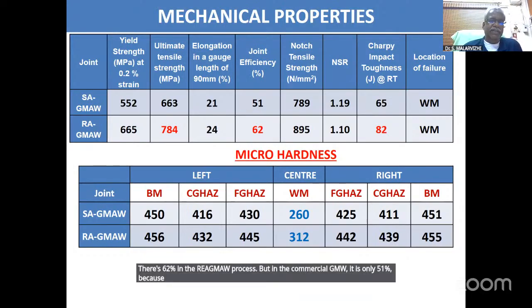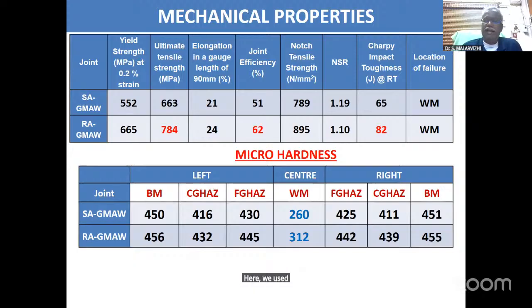Why is the joint efficiency low? Here we used only austenitic stainless steel filler. Though the base metal is ferritic, high strength steel with 1000 to 1100 megapascal tensile strength, due to the restriction of hydrogen induced cracking and other problems, CVRDE suggested using only austenitic stainless steel filler to avoid hydrogen induced cracking during service. If you use austenitic stainless steel filler, the joint efficiency will be around 50% only. So by this method, the joint efficiency is increased by about 10%.